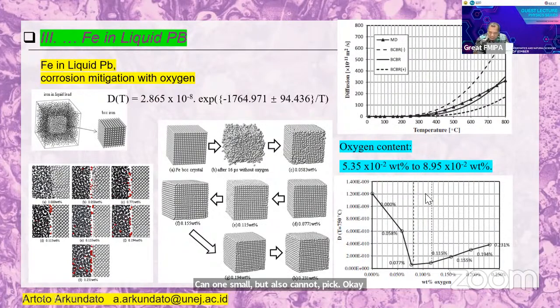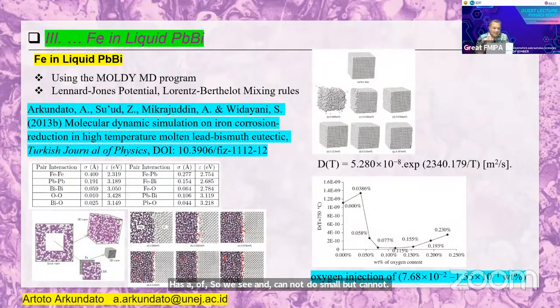We can see from this graph, there is only a small area where we can inject oxygen in the liquid lead coolant. So the point is the concentration of oxygen in the inhibitor must have a value that is sufficiently small, cannot be too small, but cannot be too high.